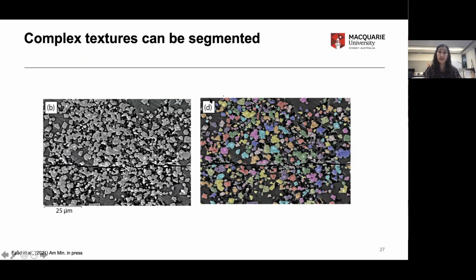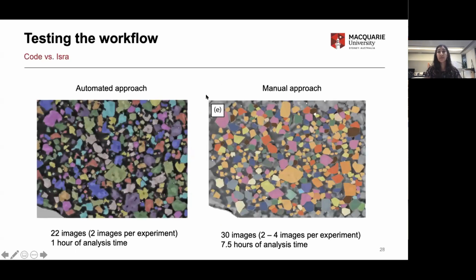So following the segmentation approach, we can end up with all of the images nicely segmented. We get areas very, very rapidly, and that was the aim of the game. But I needed to truth check my workflow and ensure that it had actually done a good job. So I decided that it was important for me to manually measure all of my images as well. And so that meant that I analyzed 30 images, between 2 to 4 images per experiment, using the areas of equivalent circles technique. I calculated later on that was probably about 7.5 hours of analysis time.